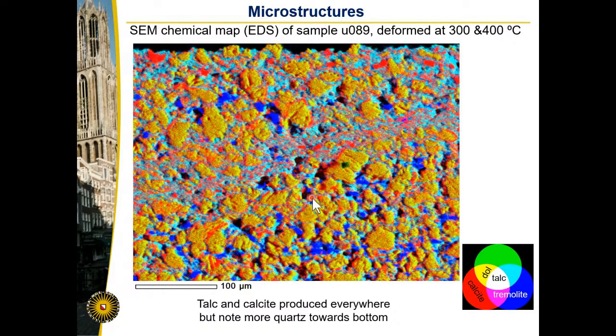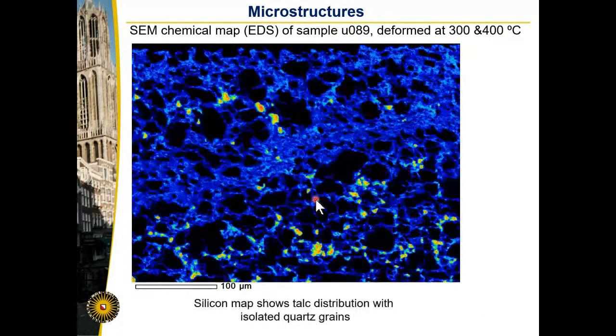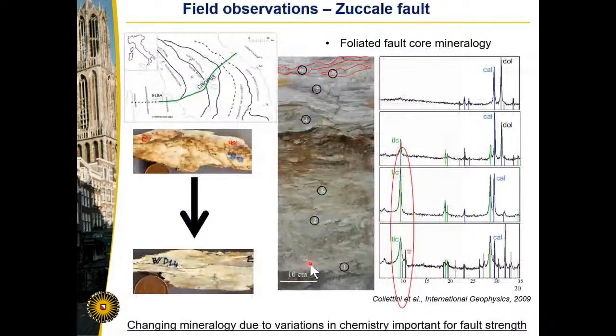And we can see that also in the silicon map. This is clearly, we see lots of talc that is being formed. And you can imagine if we are trying to shear this sample, then there should be enough low friction talc present to allow us to accommodate deformation at very low shear stress indeed. So this shows that these mineral reactions have a profound effect on long-term fault strength.